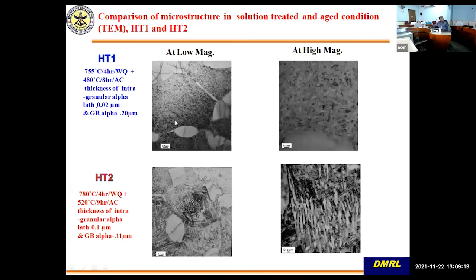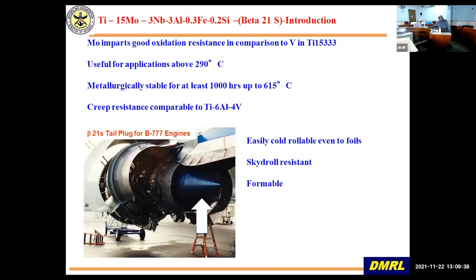Here again, I'm showing you the TEM pictures of these primary alpha and very fine secondary alpha, which you can see in TEM only. And then when you do a different heat treatment at a higher aging temperature and higher solution treatment, you can see the coarser secondary alpha precipitation laths, and that is what improved the fracture toughness.